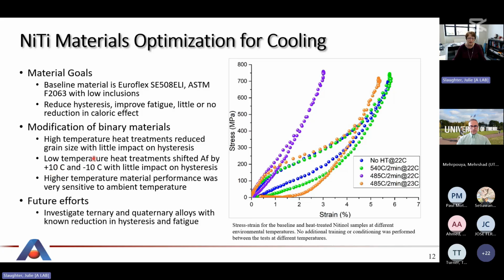And so we looked at some different options. There are low temperature heat treatments. We were able to shift the austenite finish temperature by plus and minus 10 degrees, but it didn't have any effect on hysteresis. But what this might allow us to do is to tune the materials to better perform over a wider temperature band. So that's still a good result. I just want to point out in this curve, you look at the purple here and the orange. This is the same material, and it's just 2 different days in the lab. So the temperature of that material is so close to room temperature that it's extremely sensitive to any minor changes. So just want to point that out.